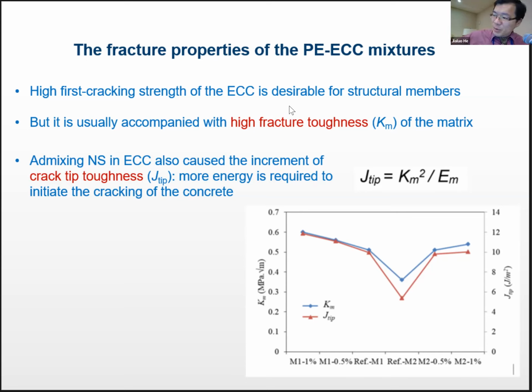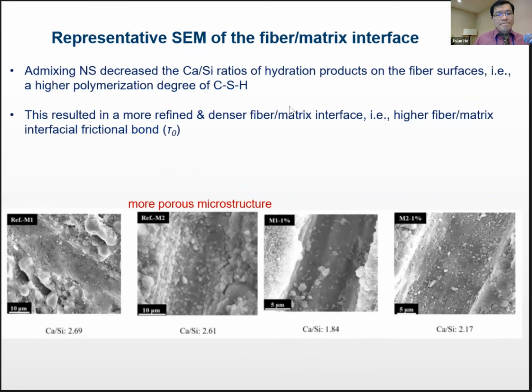So this chart is a little bit confusing because you start from the middle, you go to the left, that's the M1 series. As you increase the nanosilica, you're increasing the J tip, the fracture toughness, and the M2 is on the other side. Again, they're showing the same trend. Now, because you improve the matrix, you also hope that it also improves the bond. So that, again, is a balancing act. It did improve the bond.